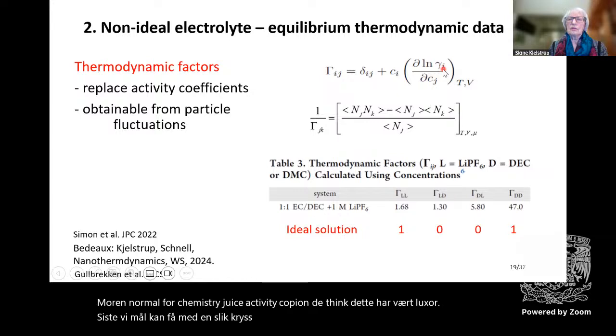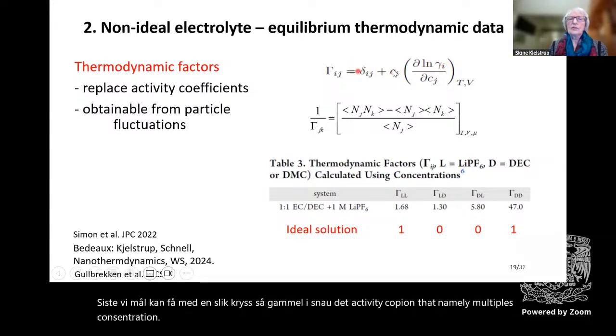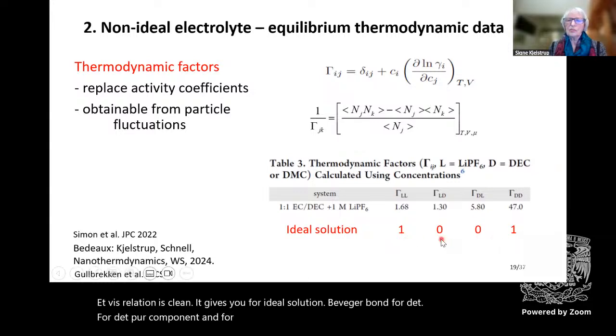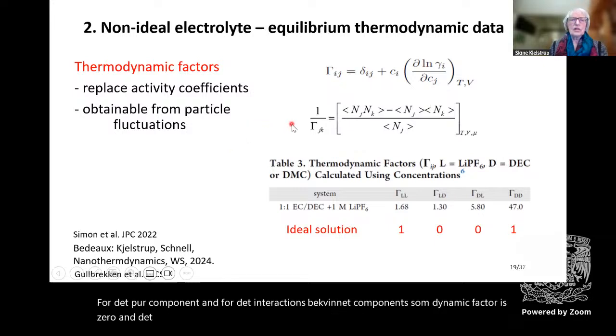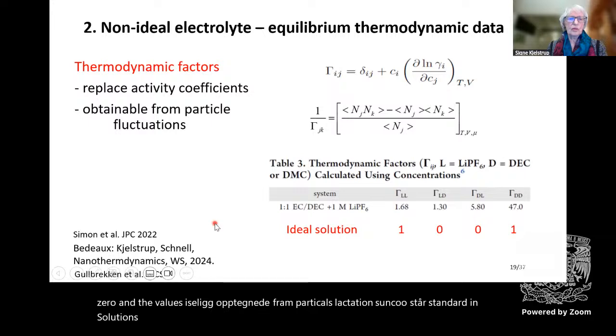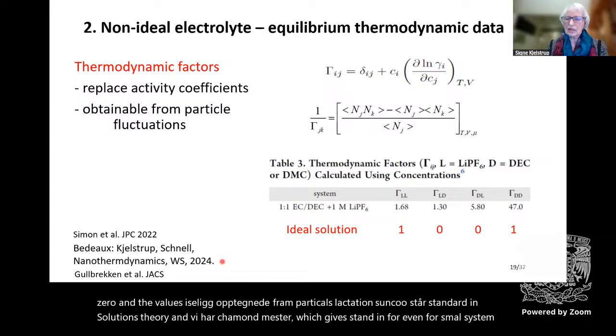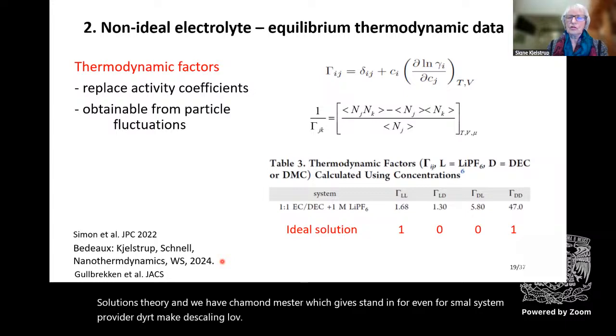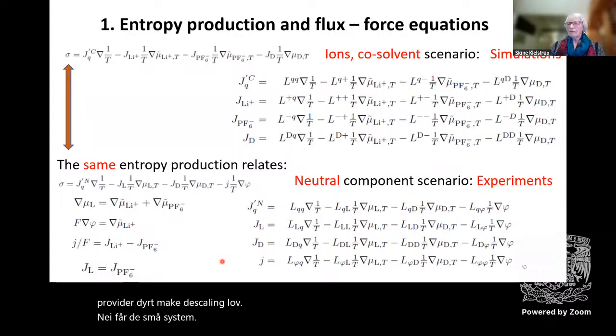So the gamma is now the activity coefficient that normally multiplies the concentration. But this relation is clear. It gives you for an ideal solution the value of 1 for the pure component, and for the interactions between the components, the thermodynamic factor is 0. And the value is easily obtainable from particle fluctuations, and those are standard in solution theory. And we have shown a method which gives them even for a small system, provided you make the scaling law for the small system. So we are approaching.